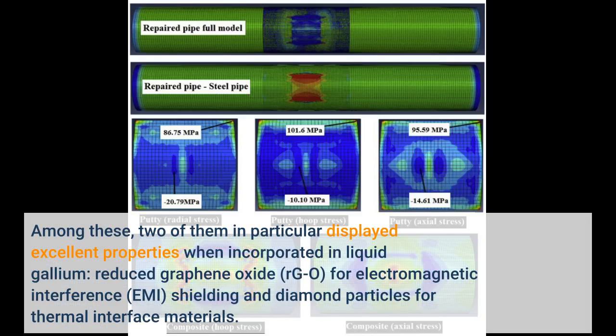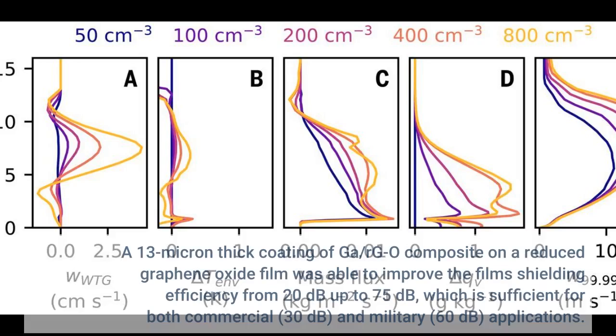Among these, 2 of them in particular displayed excellent properties when incorporated in liquid gallium: reduced graphene oxide (RGO) for electromagnetic interference (EMI) shielding and diamond particles for thermal interface materials. A 13-micron thick coating of Ga-RGO composite on a reduced graphene oxide film was able to improve the film's shielding efficiency from 20 decibels up to 75 decibels, which is sufficient for both commercial 30 decibels and military 60 decibels applications.